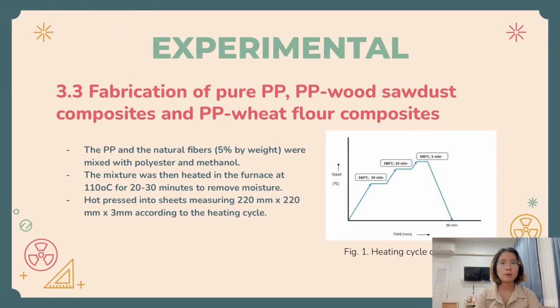Fabrication of pure PP, PP wood sawdust composite, and PP with wheat flour composite. The PP and the natural fiber, 5% by weight, were mixed with polyester and methanol. The mixture was then heated in the furnace at 110 degrees Celsius for 20 to 30 minutes to remove moisture. It was hot pressed into sheets measuring 220 mm by 220 mm by 3 mm according to the heating cycle. Figure 1 is the heating cycle of the hot press.